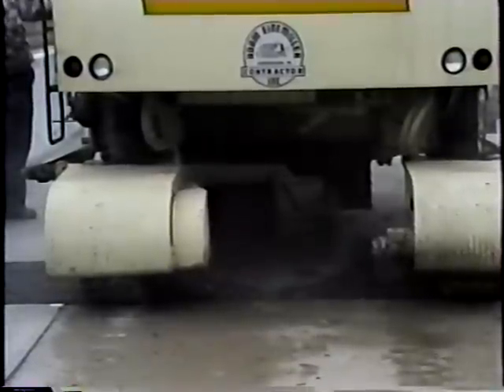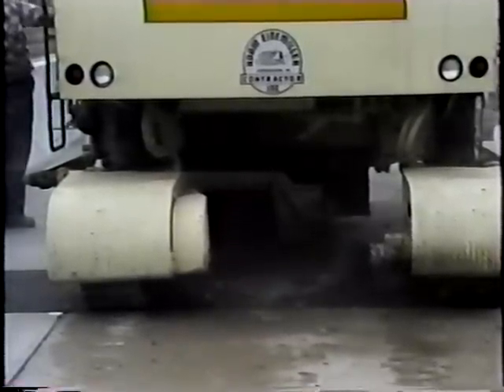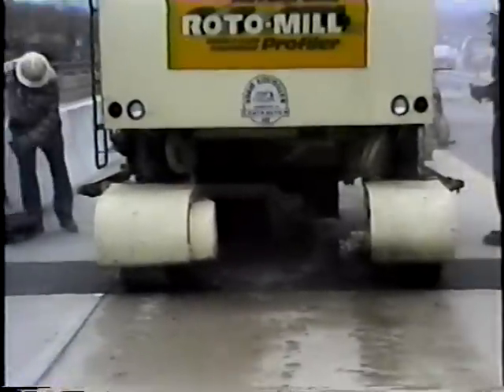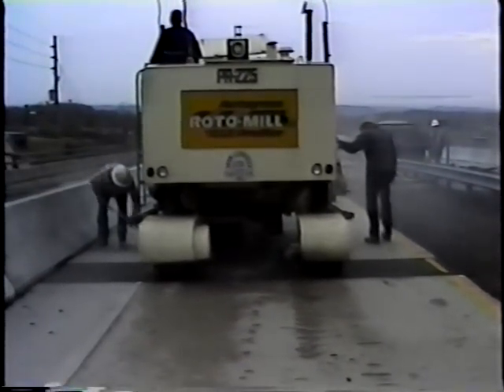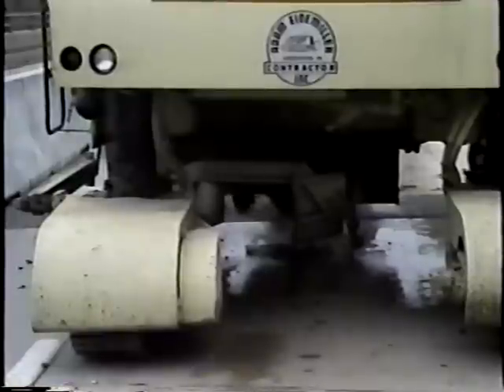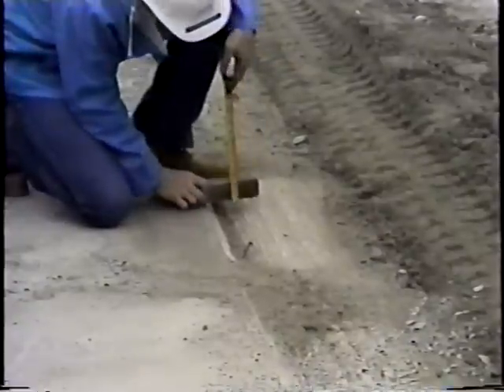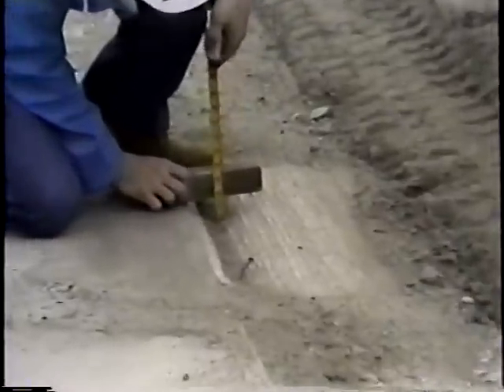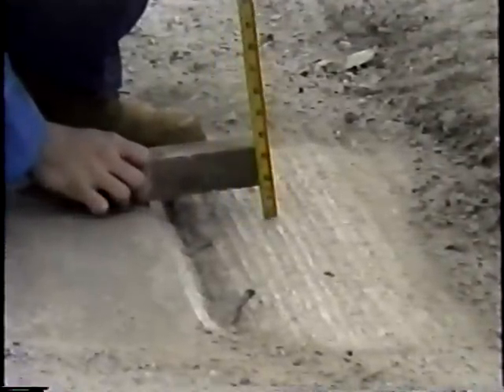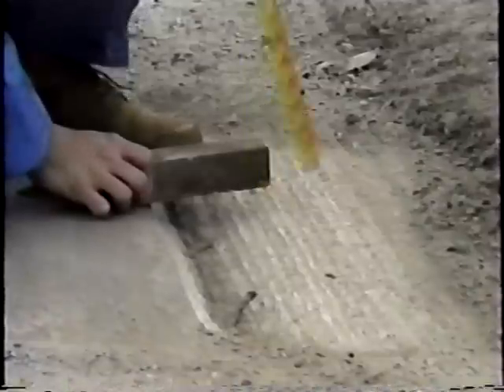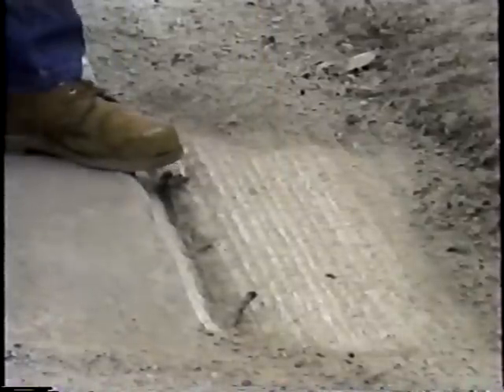Cold milling is especially effective for repairs extending across a major portion of a pavement, such as in full lane width repairs. Carbide-tipped milling machines and diamond blade grinding machines work particularly well because they can be preset to remove material to a specified depth. Although these machines produce non-vertical faces on two sides of the repair, they usually don't cause edge spalling commonly associated with feather edging.